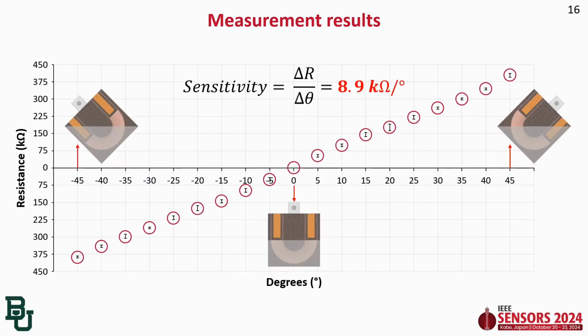The graph shows resistance as a function of the tilt angle from minus 45 degrees to 45 degrees. This graph shows us the linearity between resistance and tilt angle. Here, the resistance of the tilt sensor at 0 degrees is 1.2 ohm, and at 45 degrees, it is measured as 404.4 kilo ohm. The tilt sensor shows an ultra-high sensitivity of 8.9 kilo ohm per degree compared to conventional liquid metal tilt sensors.